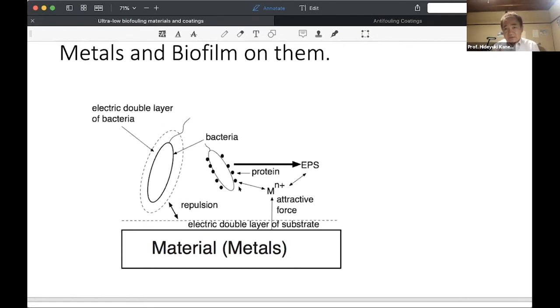For example, iron metal attracts bacteria very strongly. Therefore, from the viewpoint of a surface coating, we have to stop the dissolution of metallic ions into the environment. That is the guideline for antifouling coating. Copper, people sometimes say, has antibacterial properties. However, copper basically has a strong interaction with the bacteria. Therefore, at the beginning of the stage, copper may work, but with time, copper gradually loses its antifouling effect. Or such a discussion would be possible.